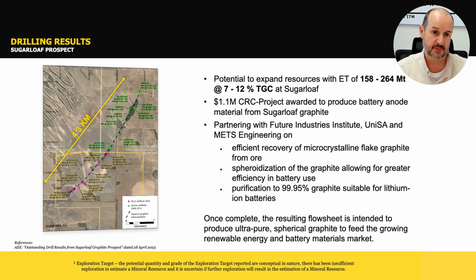And we have these experts at Future Industries Institute at UniSA and METS Engineering working on efficient recovery of that microcrystalline flake graphite from the ore and producing a high-grade concentrate of above 94% total graphitic carbon. And the aim is to get recoveries of about 80%. And then the aim is to spheronize that, so turn it into these little balls that you can use in lithium-ion batteries, and then purify it to greater than 99.95% purity. And then once we've done that, it should meet all the relevant criteria for a battery anode material.